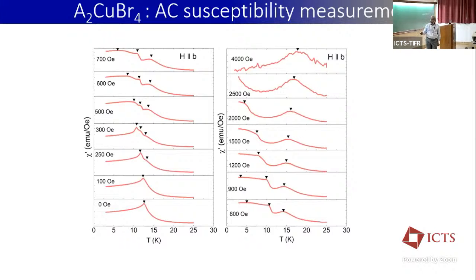As you increase the magnetic field, the phase evolves, whatever the ground state was. So you see from one peak to two peaks, then it goes to three peaks like this. And when you apply more field, because all the spins are aligned in the direction of the field, you get a polarized ferromagnet, and then you get only one peak.